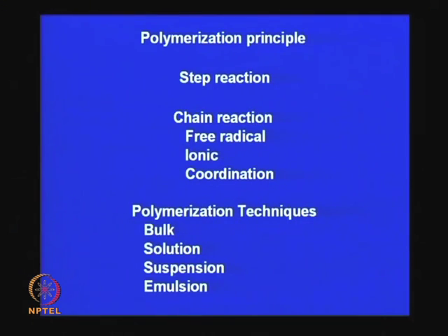So, the polymerization principle you know already. I have explained what the step reaction principle is, because these polymers are synthesized involving reaction between a carboxyl group and a hydroxyl group, or a carboxyl group and an amine group, leading to an ester or amide group. So, leading to polyester or polyamide, and I mentioned that this occurs in steps. First of all one diol reacts with a diacid to form an intermediate.